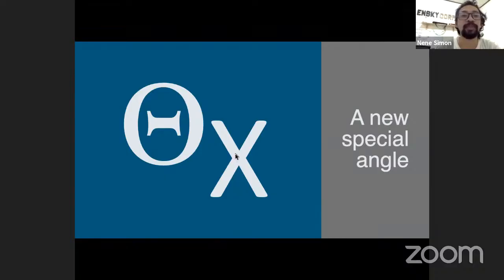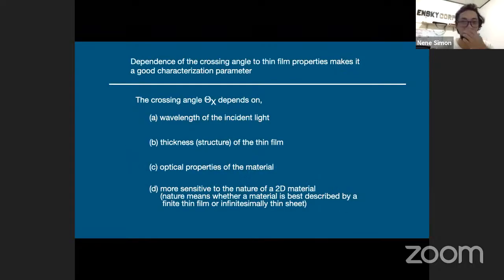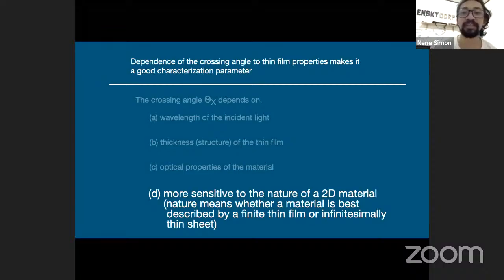Well, in this thesis, we develop a technique based on a new angle we call the crossing angle. So at the crossing angle, the degree of polarization of the reflected light vanishes. So this new angle has properties such as wavelength and material dependence. It will also be discussed that the crossing angle technique is more sensitive to the nature of the material compared to the pseudo-Brewster angle. So what I mean by the term nature is whether a material, specifically the 2D material, is best described by a slab with finite thickness or an infinitesimally thin sheet. This will be elaborated more as we go further in the presentation.